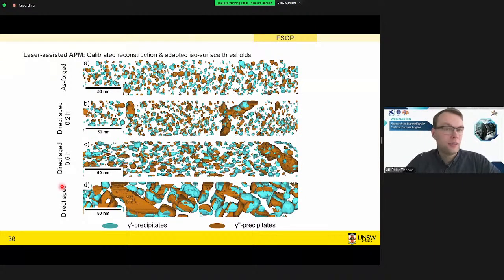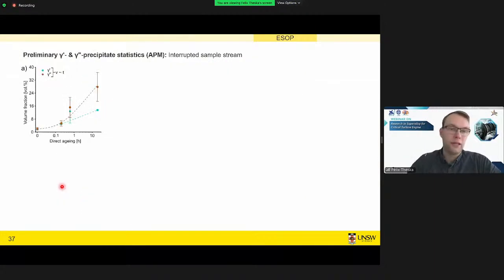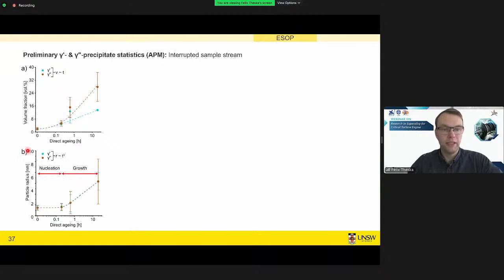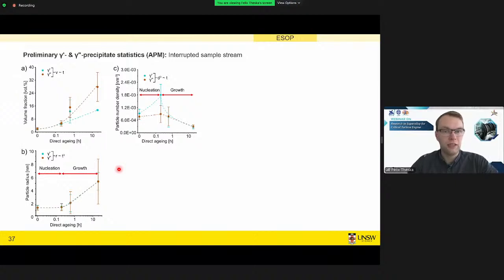All right, and now we can analyze each of these steps in terms of volume fraction, which follows a nearly linear function. We can have a look at the particle radius for the small population of these particles, which remains almost constant until 0.2 hours direct aging, and after 0.6 hours, we see these particles start to grow. If we look at the number density, we can confirm that the first 12 minutes are the nucleation regime, followed by the growth regime.